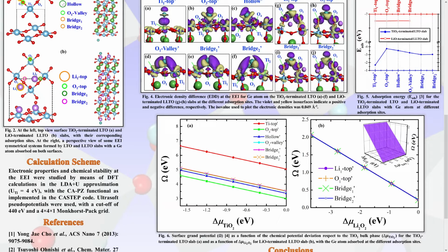Calculation scheme. Electronic properties and chemical stability at the electrode-electrolyte interface were studied by means of DFT calculations in the LDA plus U approximation, with the CA-PZ functional as implemented in CASTEP. Ultrasoft pseudopotentials were used with a cutoff of 440 electron volts and a 4x4x1 Monkhorst-Pack grid.